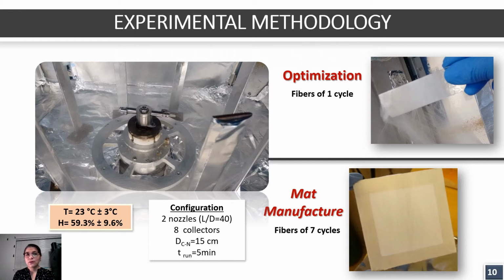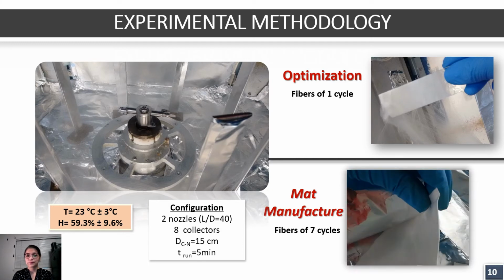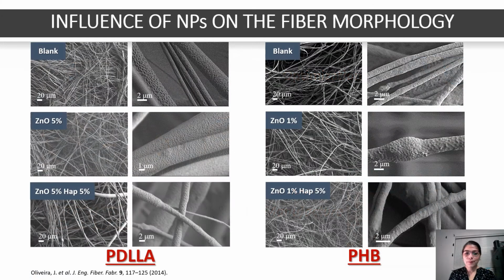Instead, for the mechanical characterization, a square metal device was used, collecting the fibers of 7 cycles. Regarding the results, in this slide you can observe the influence of nanoparticles on the fiber morphology for both polymer systems. Concerning PDLLA, the left images, it is observed that the fibers of the ternary system present a surface roughness similar to that observed in the absence of nanoparticles.